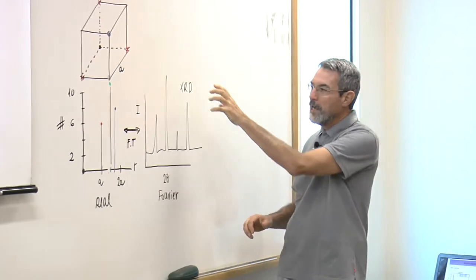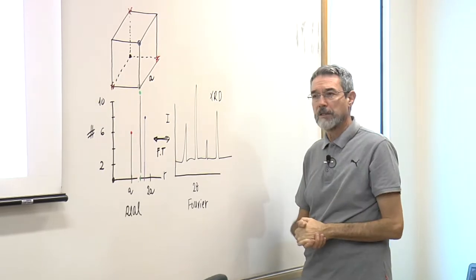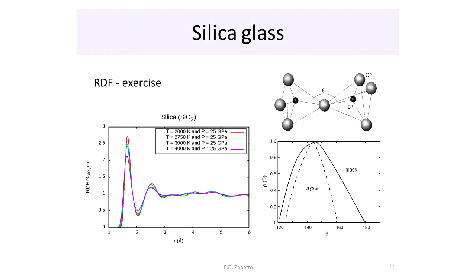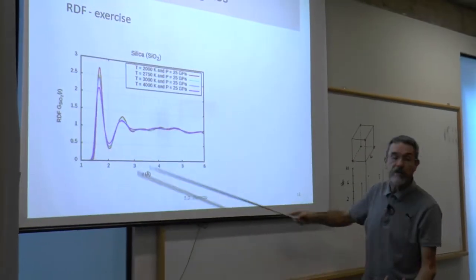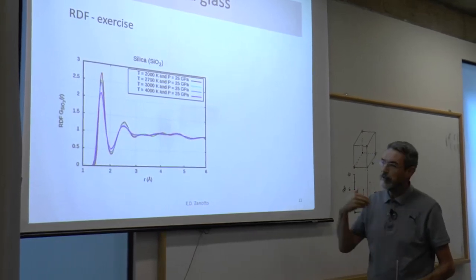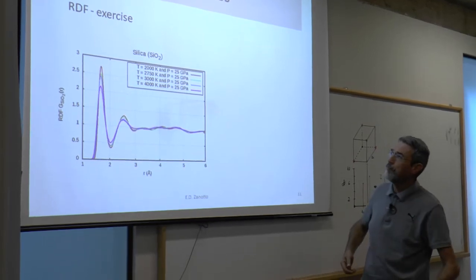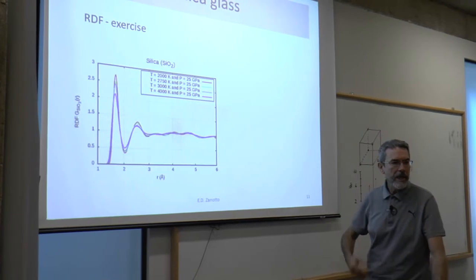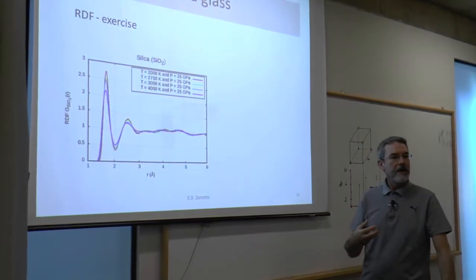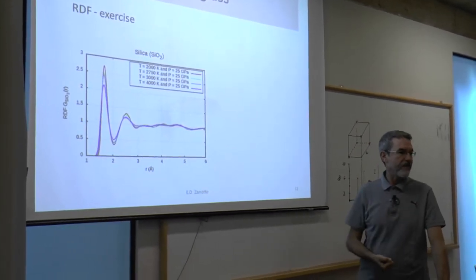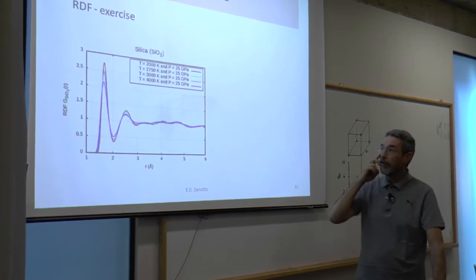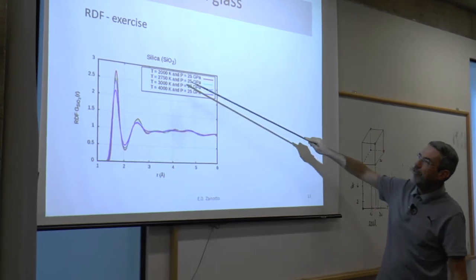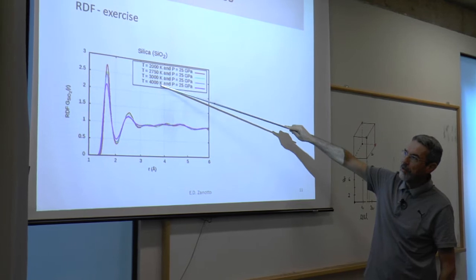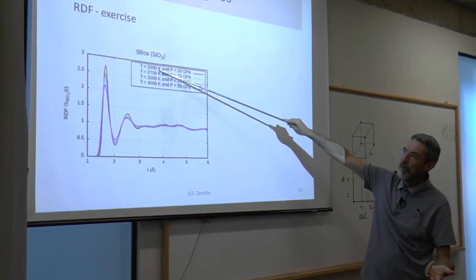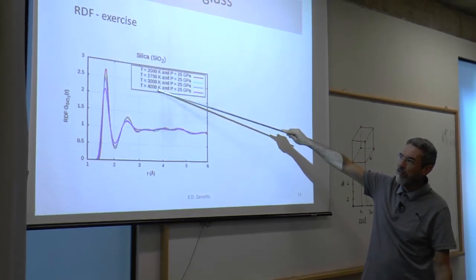What happens then if we take an X-ray diffraction or neutron diffraction pattern of a glass? This is the result. This is an X-ray diffraction of a glassy material, in this case pure silica glass. It has been filtered and calculated, but it's a clean version of an X-ray diffraction of a silica glass. In this case, they have changed the temperature, because this is a simulation. This is just a simulation, 2000, almost 3000 Kelvin, 4000 Kelvin.